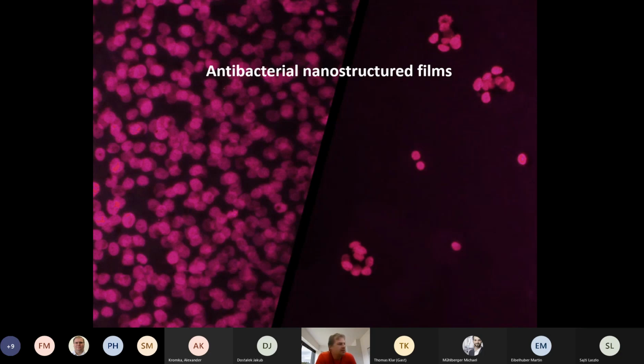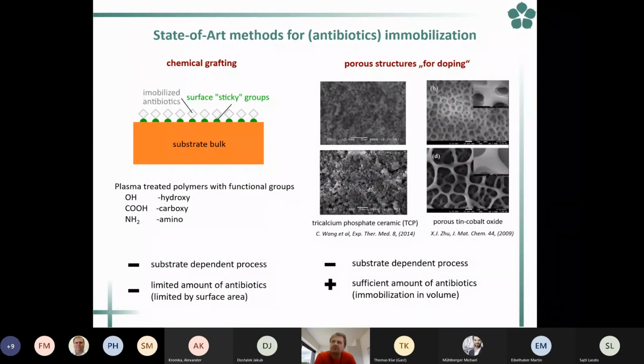Further on, where we are now active are some antibacterial nanostructured thin films. And antibacterial, nowadays also antiviral surfaces are really highly wanted. That's due to the pandemic of COVID, of course. And there are some different strategies. The first strategy for preparing antibacterial surfaces is that they are antifouling. This is usually quite closely connected with high hydrophobicity, so that no species can attach to the surface. We are doing something a little bit different, where we are using chemical grafts or films as scaffolds, which can serve as a buffer for some active species, for example, antibiotics.